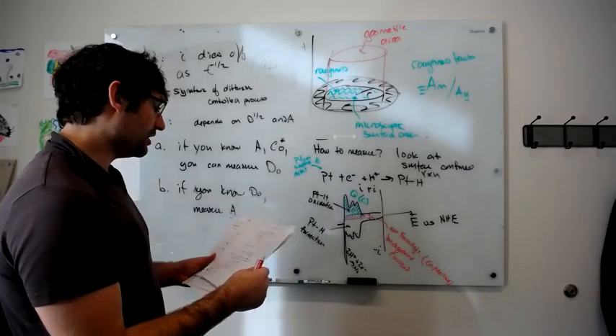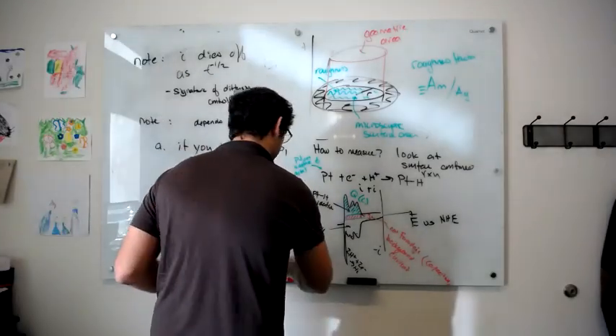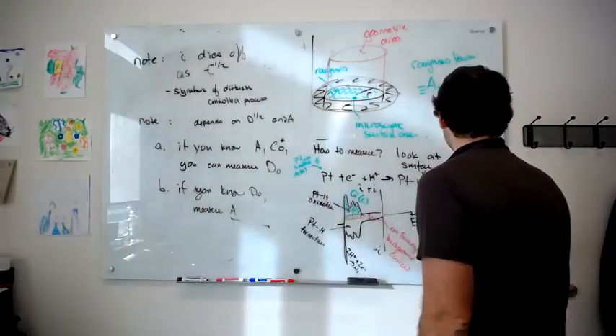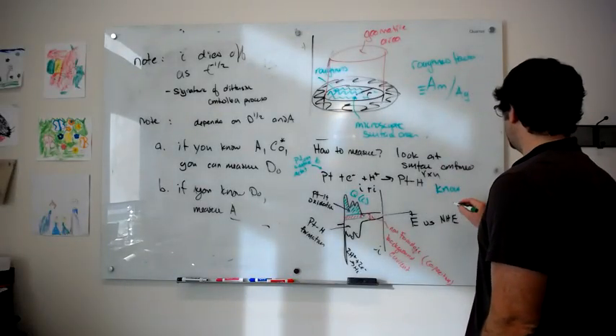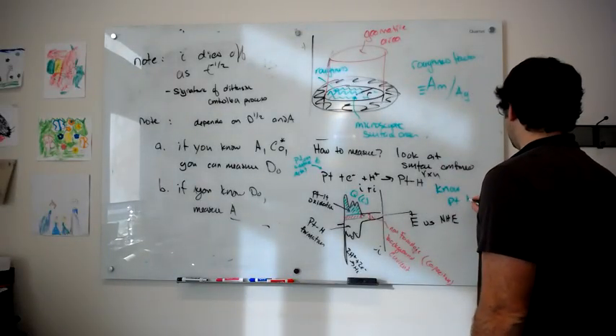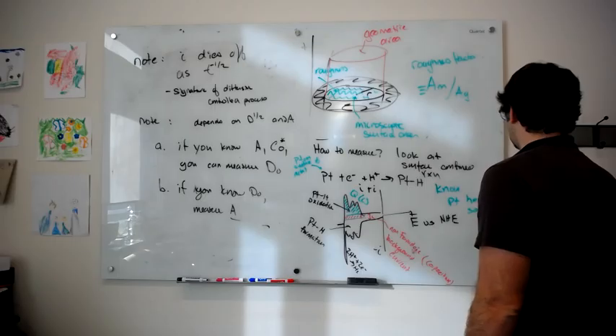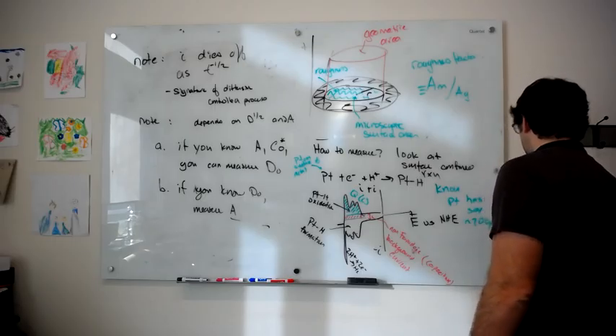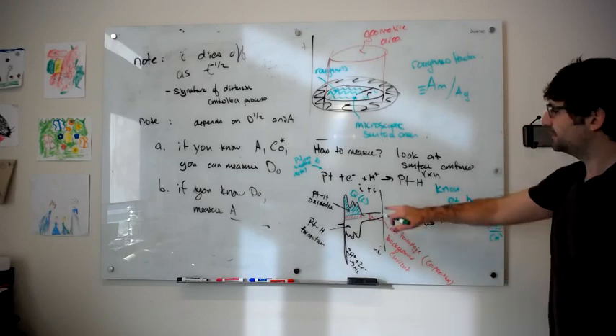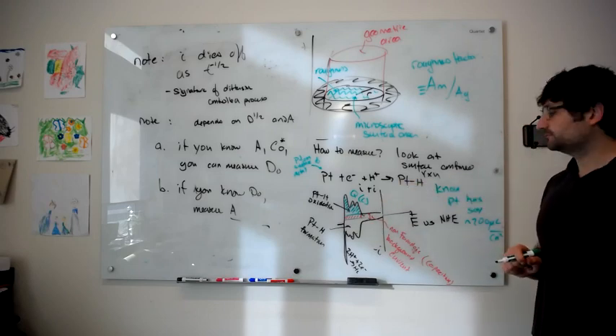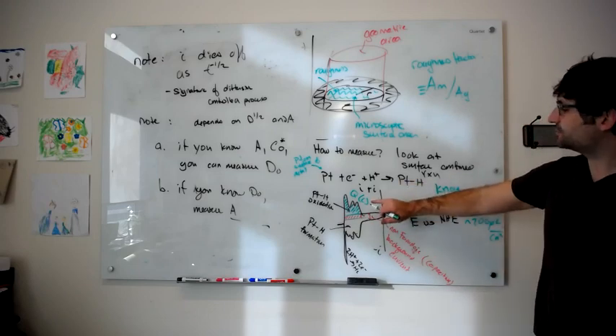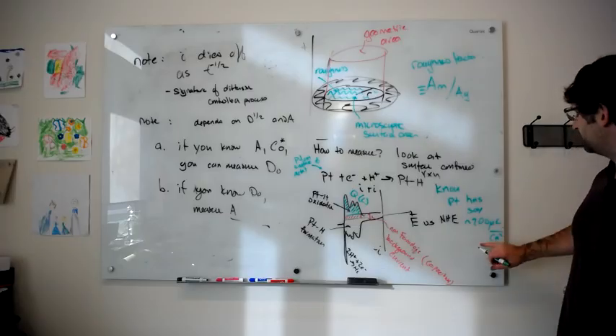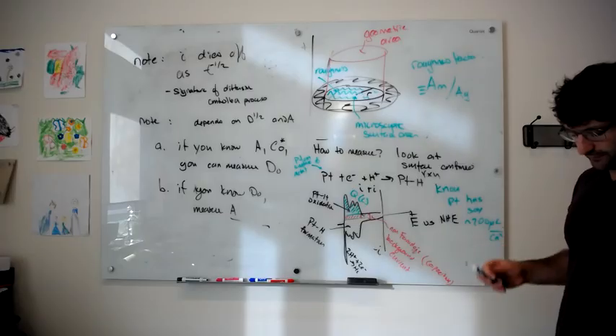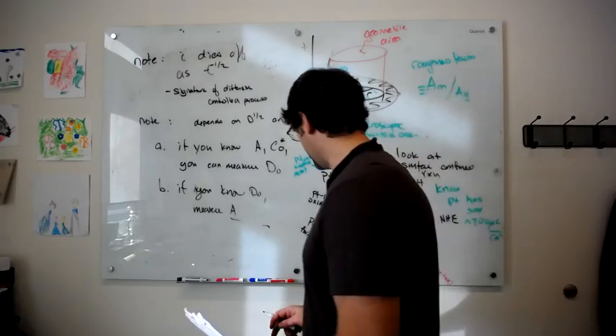And then, if you know, and this is what you do in lab, that platinum has approximately 200 microcoulombs per centimeter squared of platinum hydride formation charge, then you can calculate the total charge in coulombs, divide by this factor, and get the area of the electrode. And you can practice that in the lab.